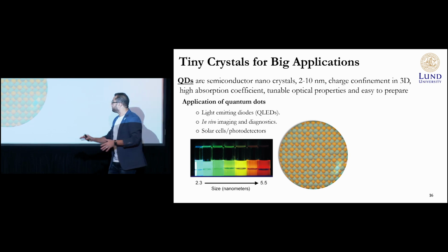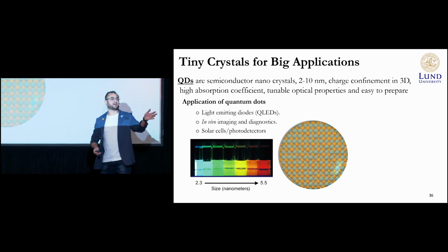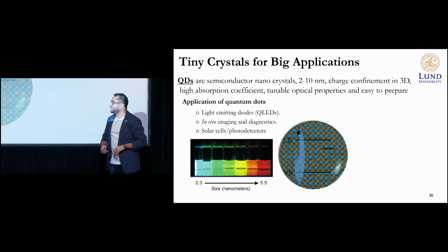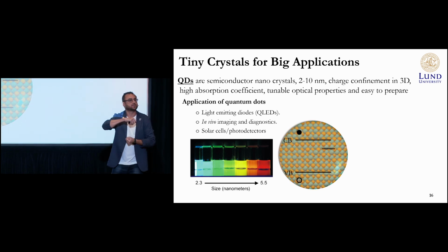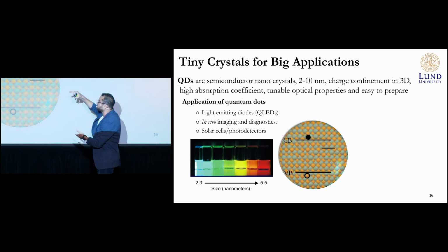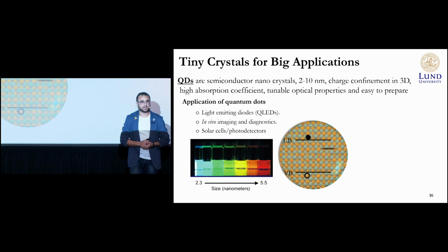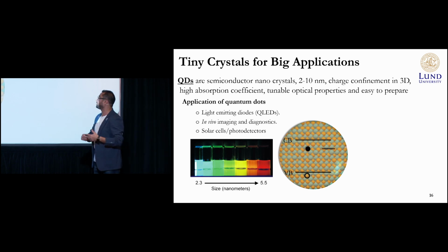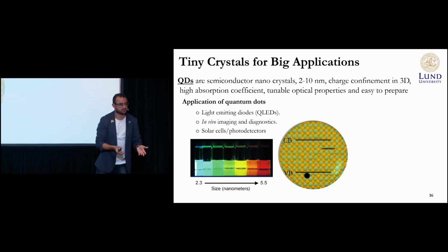In normal life, that's how a quantum dot looks: thousands of atoms arranged in a certain beautiful way. But once they interact with the light, you create excitons. These excitons will relax quickly to the conduction band minimum and valence band maximum. And at some point, if it's ideal, within 20, 30, 40 nanoseconds, they will recombine, giving light. This is the ideal case, which is not always the case.